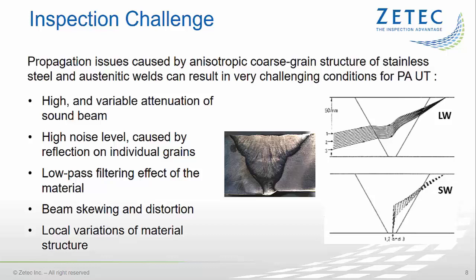The ray tracing images on the right side of this slide were generated in the 80s by physicists of the UK Atomic Energy Authority and compare the behavior of longitudinal waves and vertically polarized shear waves when propagating through a dendritic austenitic weld structure. We can see that the L wave beam somehow changes direction, but it will effectively propagate through the weld. On the contrary, the shear wave beam literally plunges into the weld root and will therefore not detect flaws on the far side of the weld. Of course, this is only one configuration, but it clearly illustrates the challenges that we are facing when inspecting austenitic welds. It also shows that we need to drastically adapt our inspection techniques to be successful in these configurations.